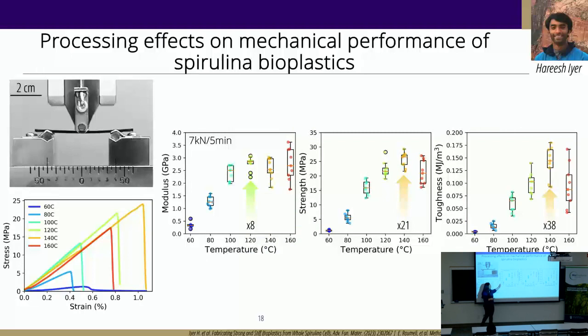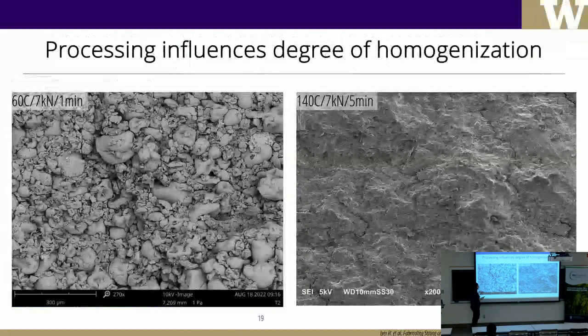So then if we extract the data for modulus, strength and toughness, and this is the work to fracture basically, not fracture toughness, you can see that we have significant ability to play with the properties that we get. About 8 times you can improve your modulus, about 21 times your strength. And I do want you to look also on the y-axis for a second, because you may think that these are very, very weak materials. These are weak for polymers, but they're not that soft and weak. They're not the squeezy category. We are talking about strengths all the way up to 25 megapascal and moduli 2.5 GPa. So that's quite, and 1% or less, actually, elongation to break. So we're talking about very brittle, relatively stiff, and relatively strong. I will say plastics now and bioplastics, because those do flow with heat and pressure. So now I allow myself to say bioplastics because they do have the plastic behavior.